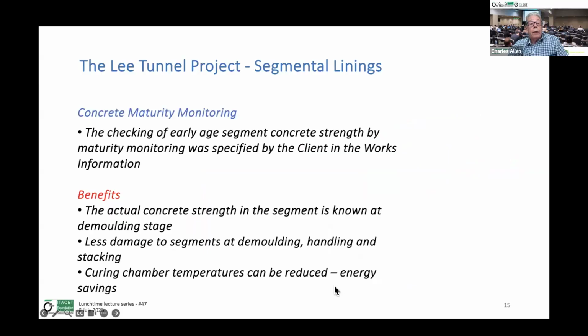We also incorporated maturity monitoring for the checking of early age segment concrete strength, and we also specified that in the works information. And the benefits are the actual concrete strength in the segment is known at demolding stage. You're not trying to crack a cube.